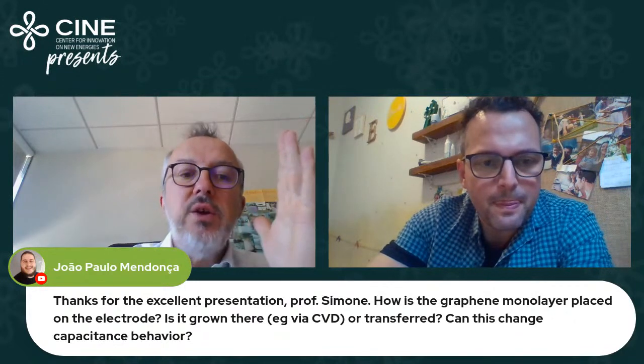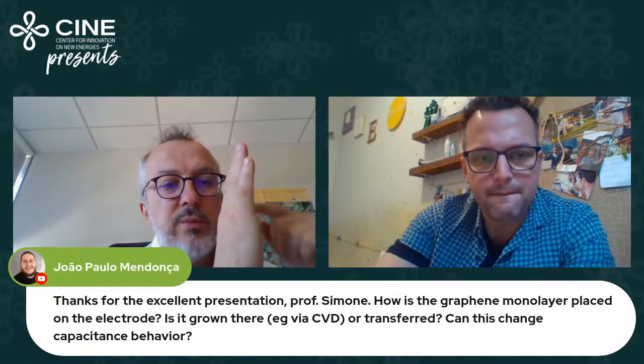Maybe you can read this. So I tried to explain that; you have all the details in the paper. This is the transfer. The SLG is grown on a copper substrate. Then you put a PET film onto it by pressing. You dissolve the copper so that after that you end up with PET with the graphene on it.